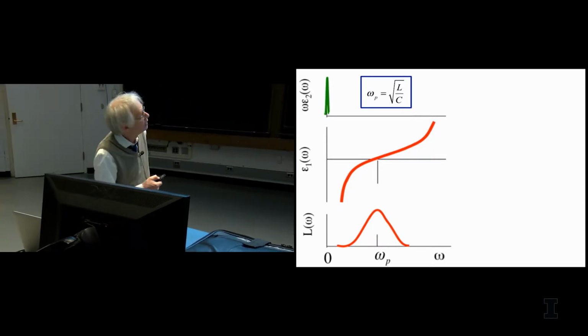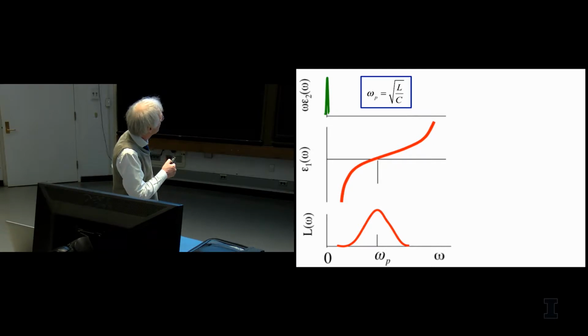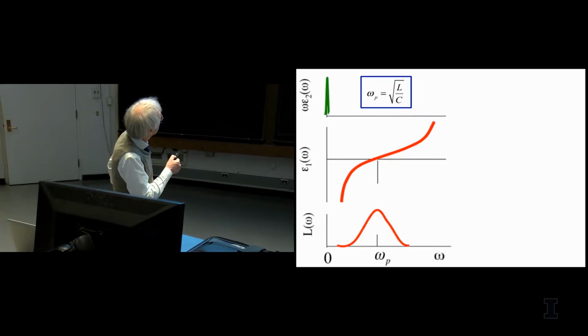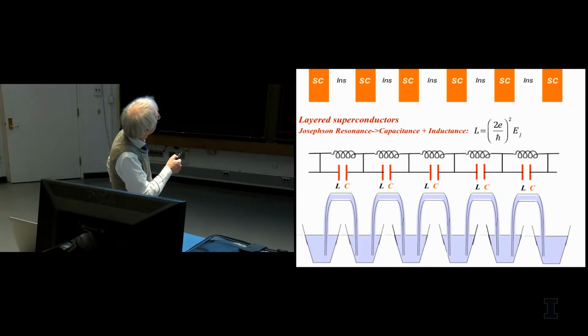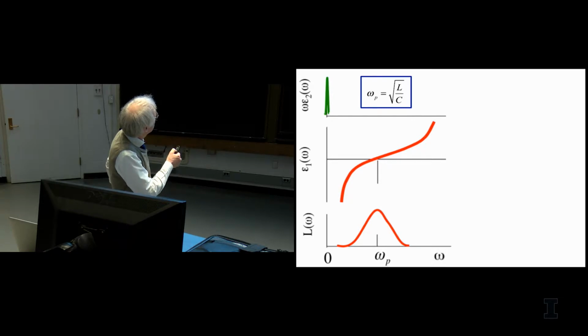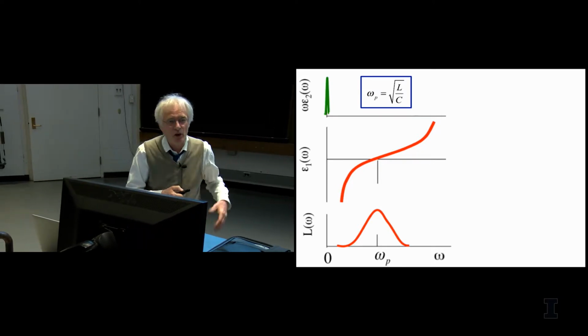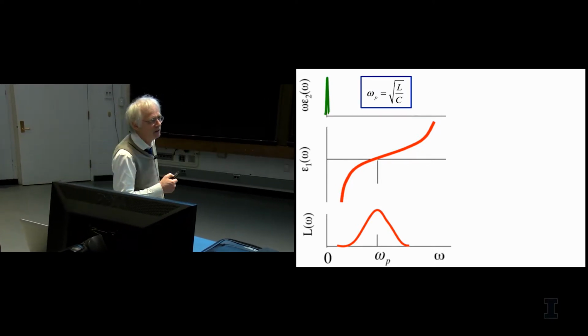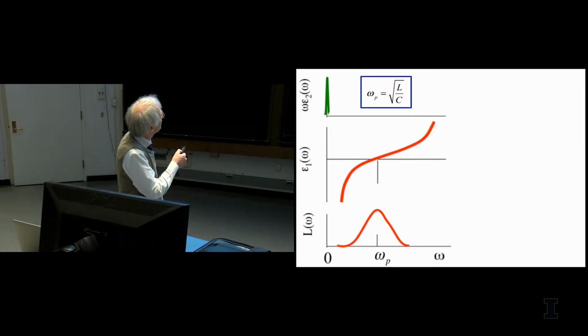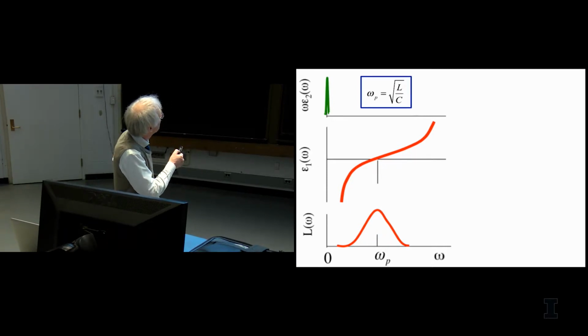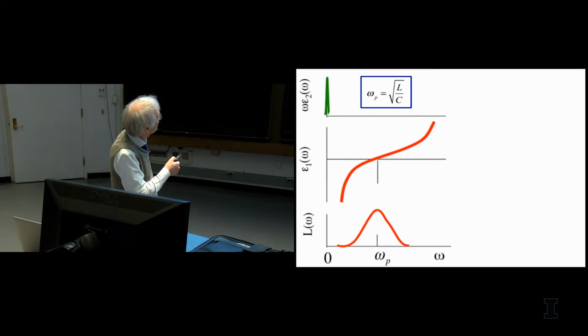If you do an optical experiment, you measure the real and the imaginary part of the dielectric constant, epsilon 1 and epsilon 2. If you take omega times epsilon 2, you get something that we also sometimes call the optical conductivity. Along the c direction, between the planes, you would have just a small peak, because of the superflow from one layer to the next. Of course, the connection is only very weak as a Josephson coupling, so there's not much spectral weight in this peak. And then at some low frequency below the gap, we have a crossing through zero of the dielectric constant. That gives rise to a plasmon.